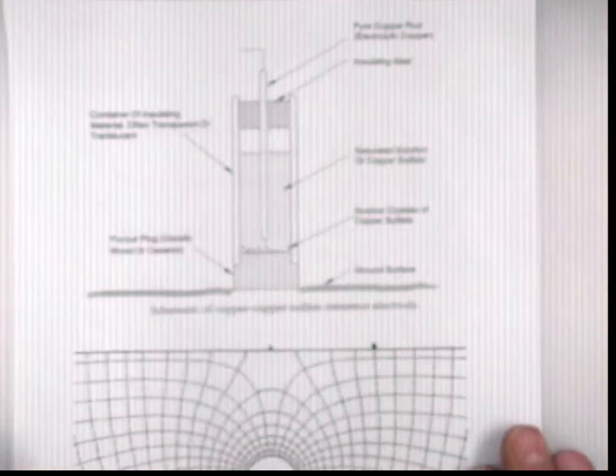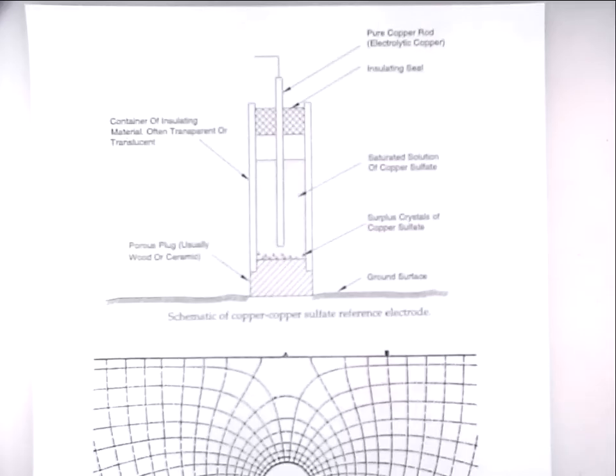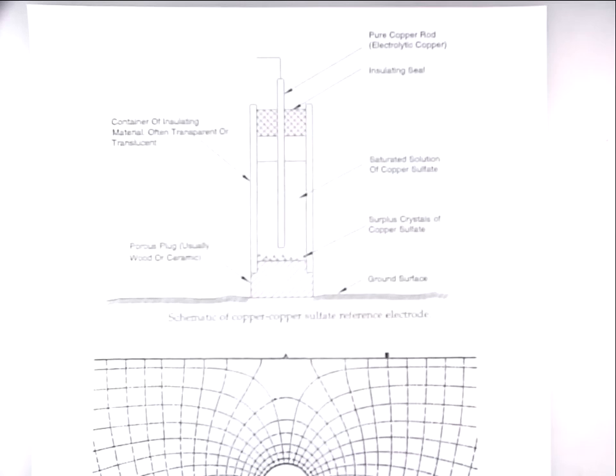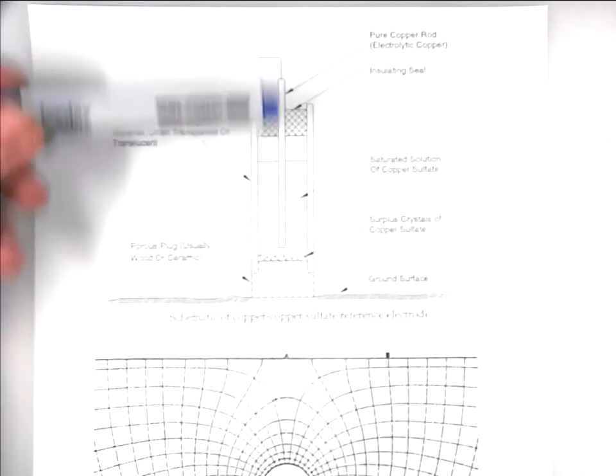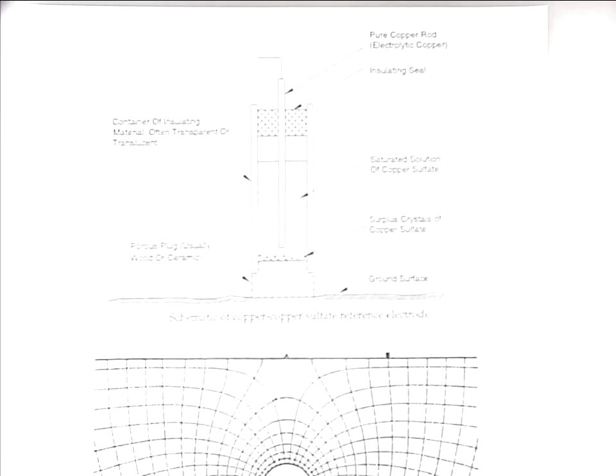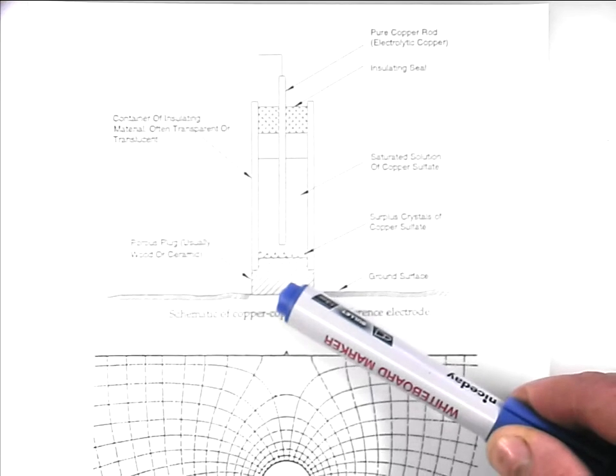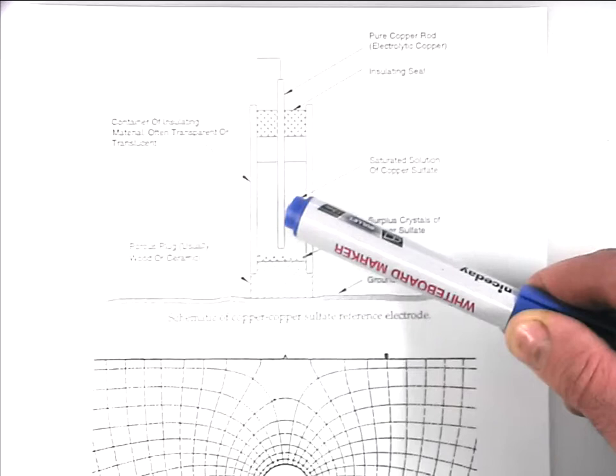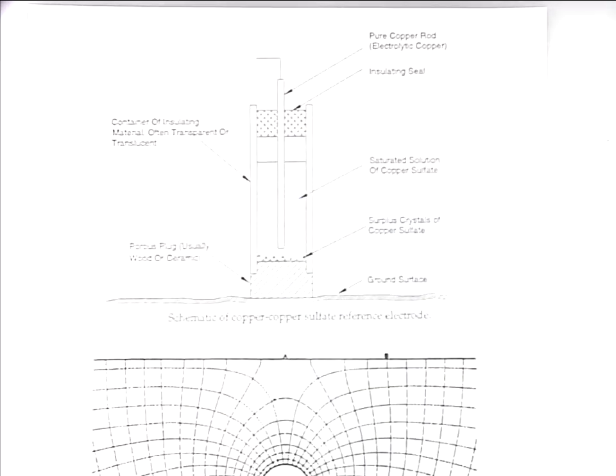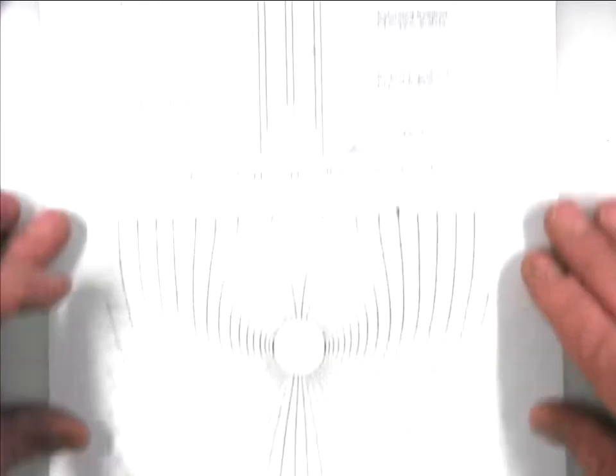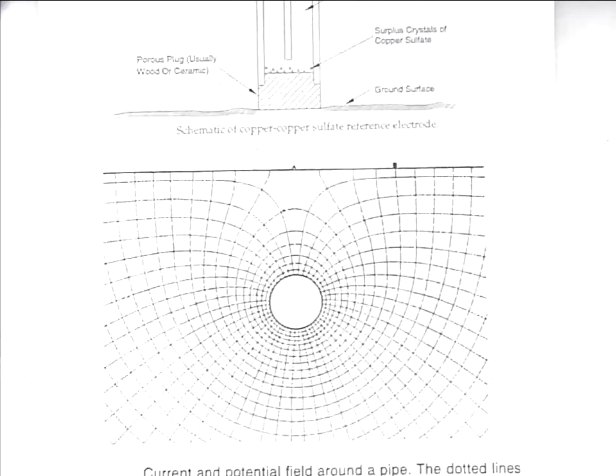and that electrode has a standard potential against the standard hydrogen zero value. And then the sort of things that you can do with that, this is a section showing a plot of potential round a pipe. So this pipe is coming horizontally out through the board, and this is the field in the earth around the pipe. That's measured by having one contact on the pipe, one contact on the reference electrode, and using a voltmeter to measure the potential at various fixed distances away from the pipe, and then plotting the graph. So you can get potential field data, and that gets interesting once you start getting pipelines intersecting each other. So you want to know what the potential gradient is around your pipe, and you want to know whether your pipe field is affecting somebody else's pipe. That's also very common in places like the UK, where we've got pipes intersecting all over the place.